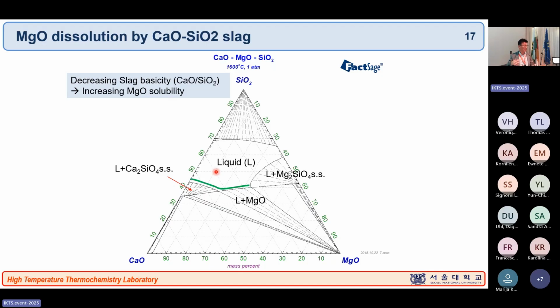And if you go to the quaternary and the quinary system, and you know the certain amount of the constant value, you can use the same idea and read your diagram. So for example, at this composition we see that this is only a single liquid phase area. And here you can have a liquid plus MgO two-phase region, of course. And all the dotted lines show you the tie lines of the two phases. Okay, so now this line here is the Ca2SiO4 saturation because it's connecting with the Ca2SiO4 plus liquid. And this is the liquid composition saturated with the MgO.